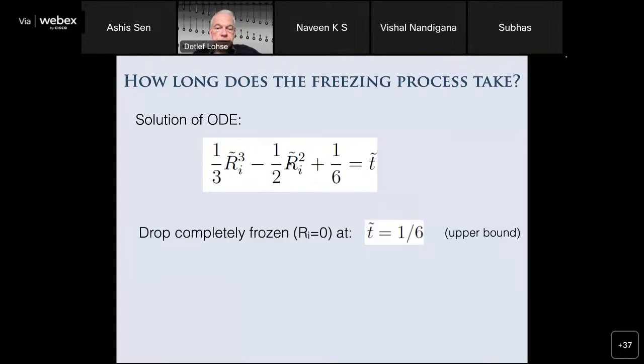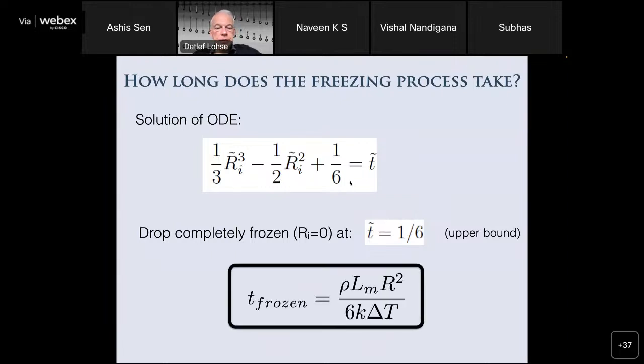And you can immediately see when the drop is fully frozen, then this radius is down to 0. And you see that in dimensionless time, the time is 1/6. So you immediately can read this off. And when you then translate this to dimensional units again, you see that the freezing time goes like r squared.